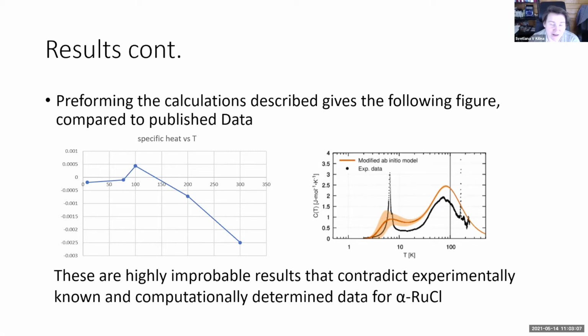Please explain. One of the leading theories of what causes that large spike you see at about 8 Kelvin in the experimental data is that there is an interaction that arises from the off-diagonal components of the electron density, and by using a collinear method, we ignore that and treat it as non-existent.